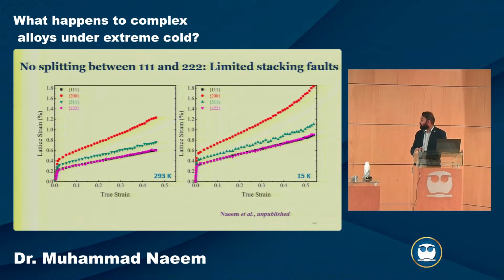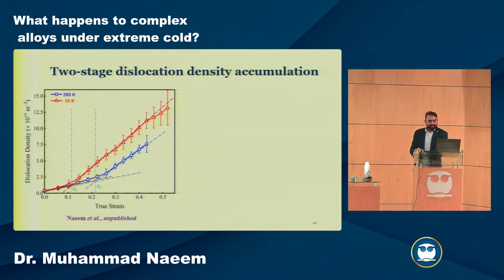You see at room temperature on the left and 15 Kelvin, that I have shown, these two, 111 and 222, they overlap at room temperature, for example, for the first case which I showed you. But here, even at low temperature, it has a very similar trend. And with the TEM, we also found that it's only dislocation slip. There is no stacking fault, there are no twin faults. And then we quantified its dislocation density, and it showed a very interesting trend.